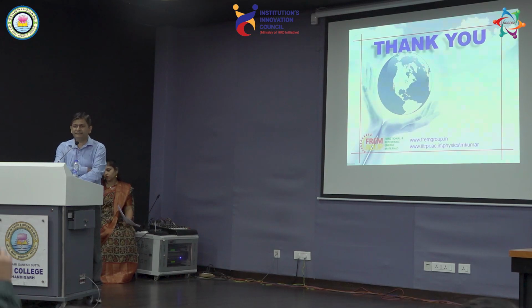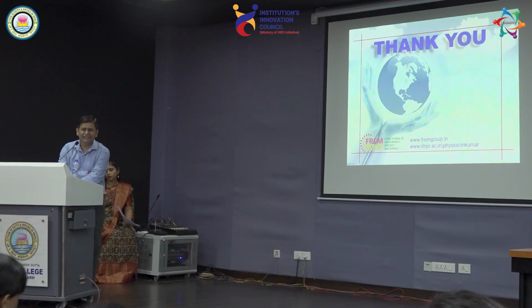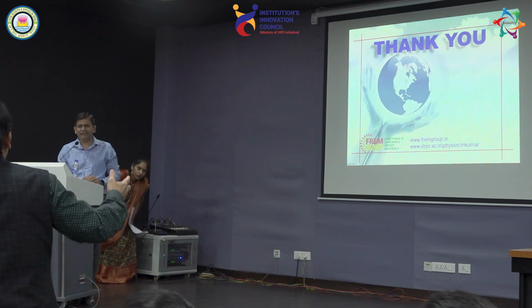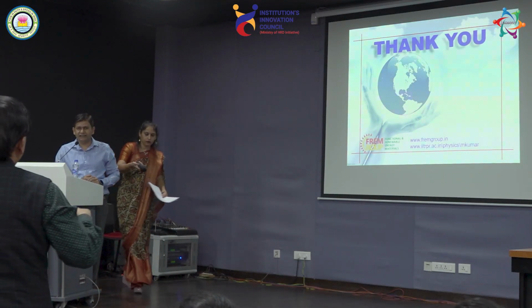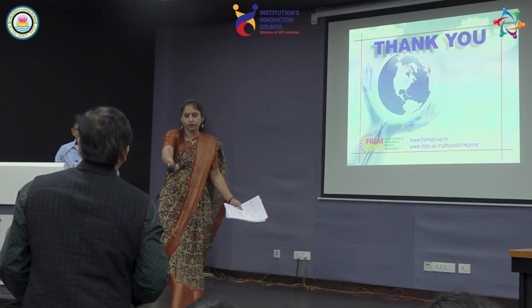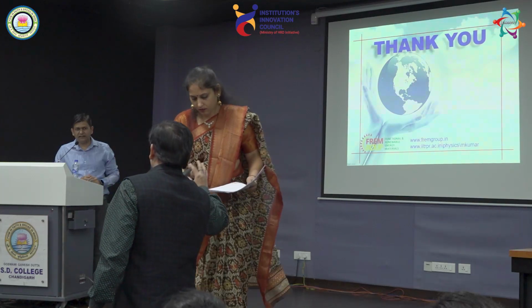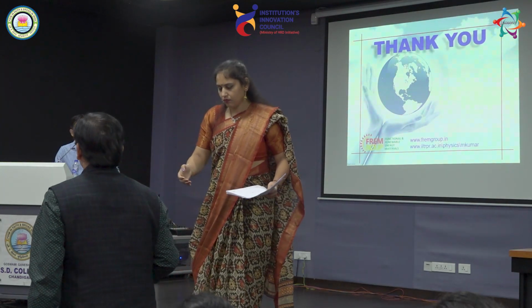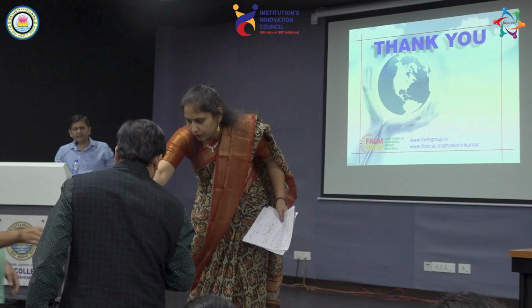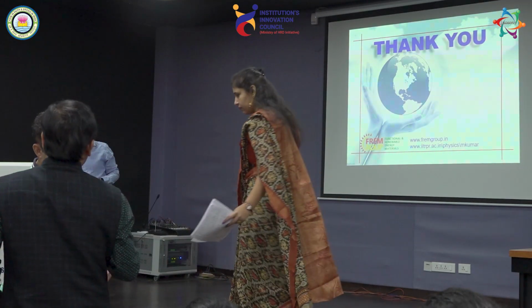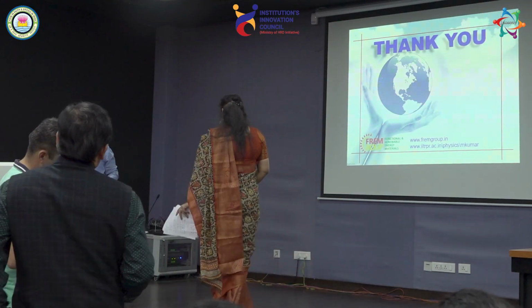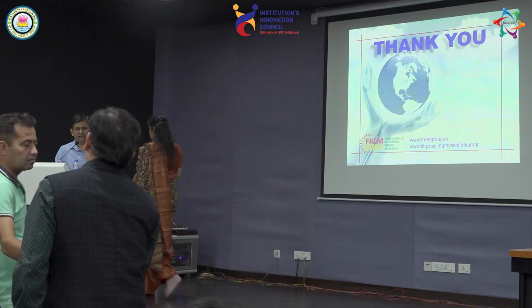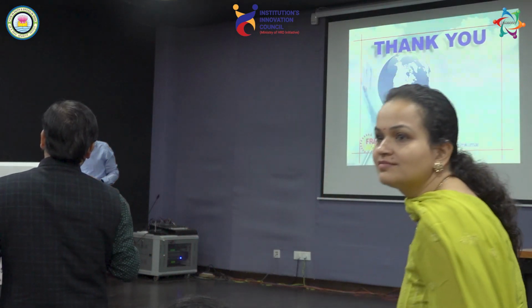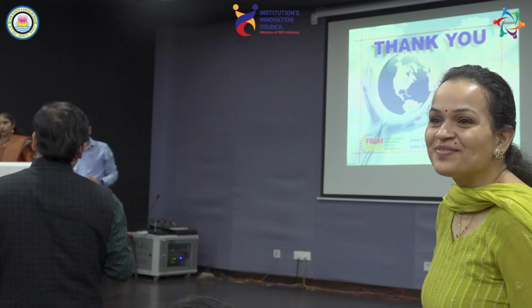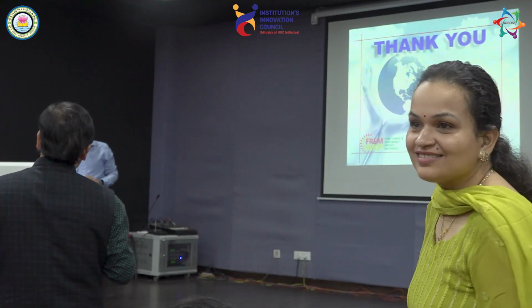Any question? Yeah, please. Regarding the MoS2 shown by the SEM, the vertically aligned MoS2, what is the delta K? I mean, how many layers are there? Okay, so the number of layers is actually 5 to 7. That was confirmed by HRTEM. More than 5 layers is, in principle, not a confined state. It may be called a 2D.